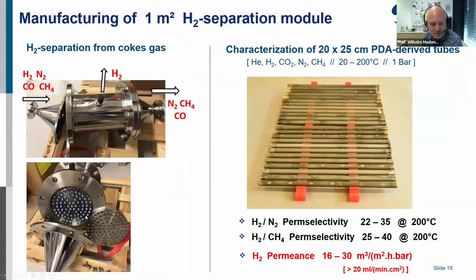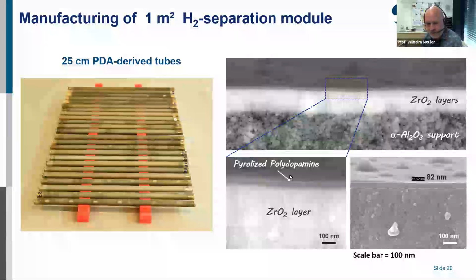So we have here a module, and in the final step, we have 100 tubes. The tubes are between 10 and 25 centimeters, in this case 25 centimeters. And you cannot see the coating because the coating is on the inner side of the tubes. That means a carbon layer, and hopefully we can demonstrate later also in the large module that we are able to separate hydrogen, for example, from these gases. We tested the single tubes. They are working, but we have to test now in the real application if these membranes are working there. And also here we use the pyrolyzed polydopamine layer. So that means the carbon layer.